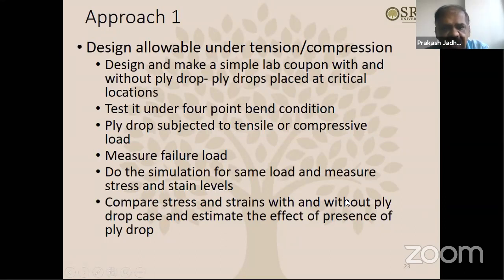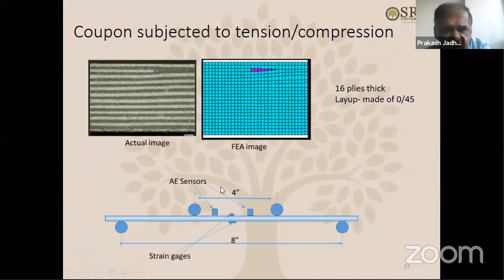So this is the approach that we followed. Maybe I'll explain again. What we do is we make the coupons, we test them. Coupons are made with and without ply drops, okay? And then we also go to the simulation, and from the experimentation, we get the initiation failure load. So the initiation failure load we apply at the end in the FEA simulation, and then we see the strain levels occurring there, for the initiation failure load for without ply drop coupons and with ply drop coupons, and then we see how much is the difference.